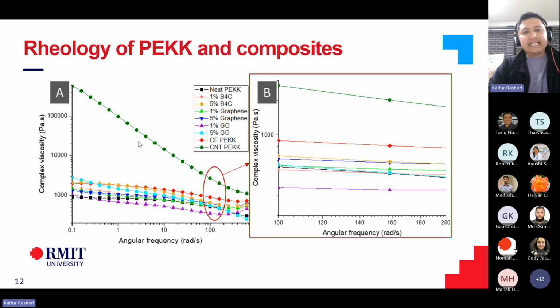So over here, you'll see neat PEKK, and also a lot of the composites, the boron carbide composites, the graphene oxide. And I also used commercially available filaments. I pelletized them, and I studied their rheology to basically develop a benchmark. So as you can see, the green one on top here, that's a CNT PEKK, which shows a significant amount of shear thinning. And all the formulations that I developed were below CNT PEKK, so we can automatically assume that they were all printable. But there's some issues here as well.